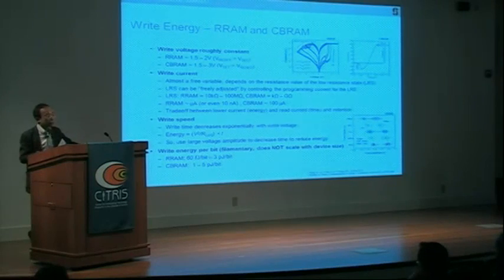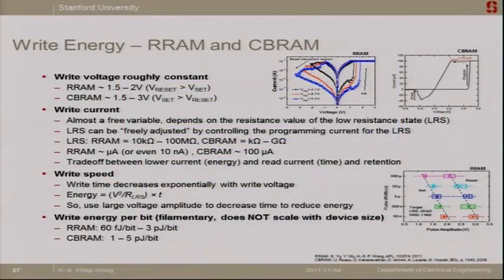Okay. Now for write current, it's really more or less like a free variable because it really depends on the resistance value of the low resistance state. When you try to write from low resistance state to high resistance state, that's when you burn the most power because your resistance is very low, so the current is very high. The resistance of the RRAM and the CBRAM ranges from tens of kiloohms all the way to gigaohms, right? So that has a tremendous range.